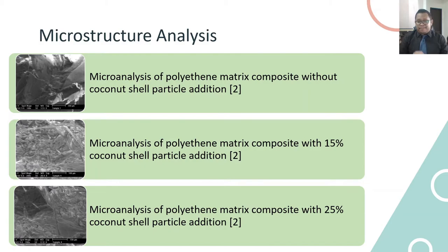For the first figure, it represents the microanalysis of polyethylene matrix composite without coconut shell particle addition. The second figure is the microanalysis of polyethylene matrix composite with 15% coconut shell particle addition. And the third figure shows the microanalysis of polyethylene matrix composite with 25% coconut shell particle addition. From the figure, we can see that with an increase in the content of coconut shell particle, the homogeneity between the coconut shell particle and the matrix will decrease.